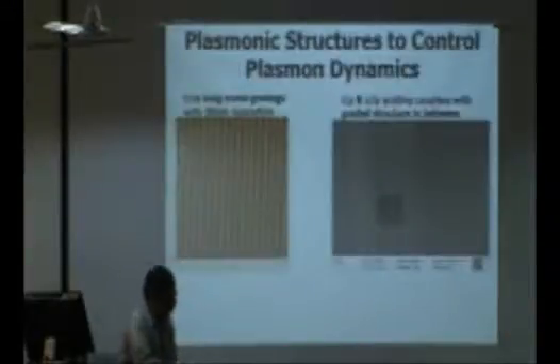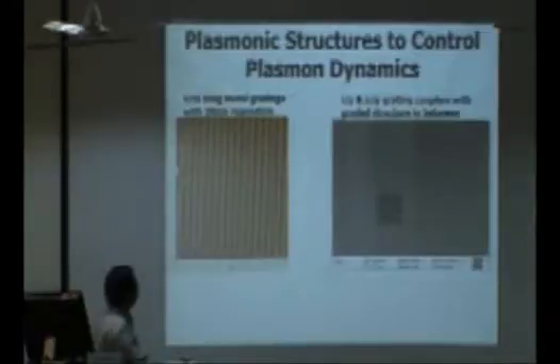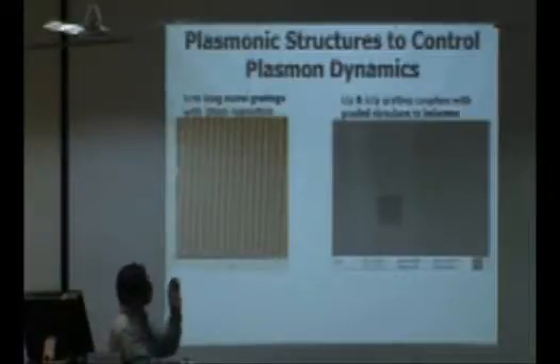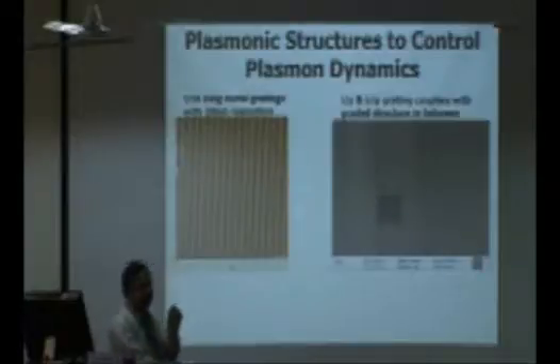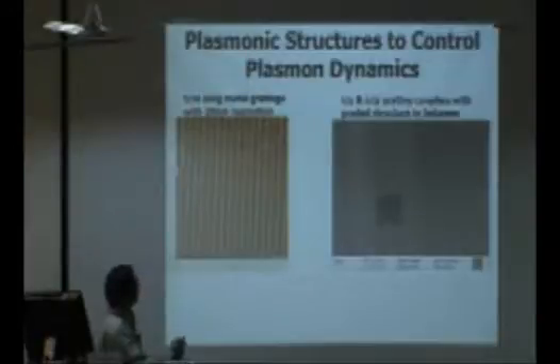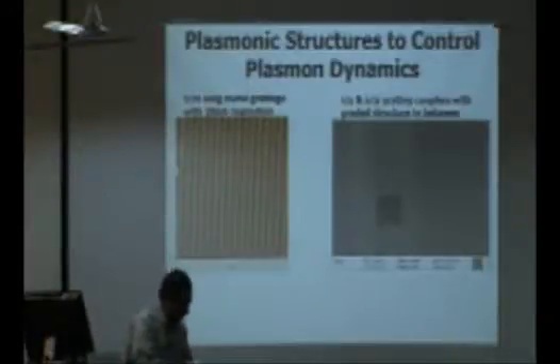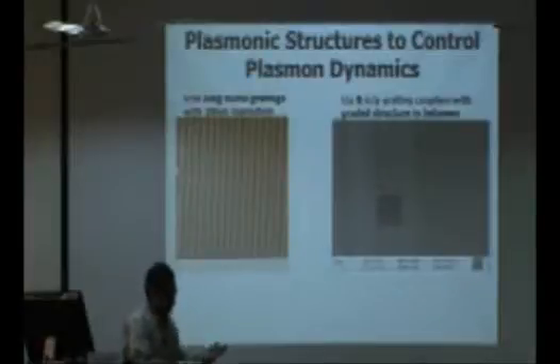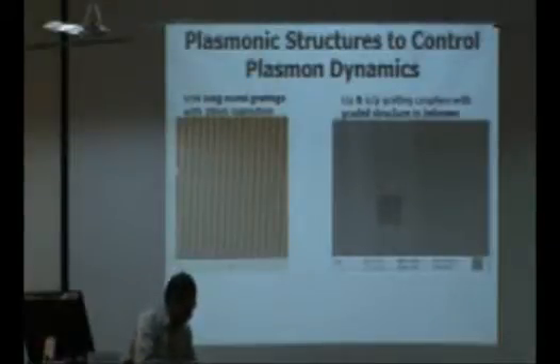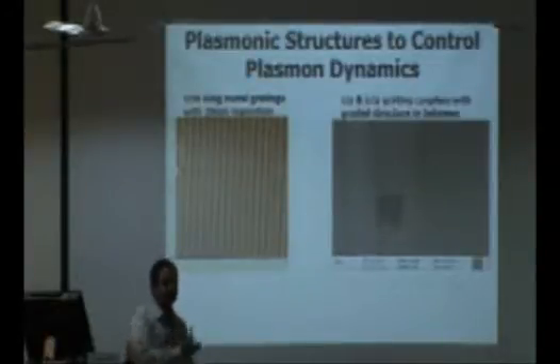So we also look at novel plasmonic structures. For example, these are incoupling and outcoupling gratings, and in between we have this graded grating structure, which is designed such that from one period to the other the period is kept constant, but the groove width is changed by a precise 10 nanometers. So the idea is to look at plasmon dynamics using these kinds of structures. For example, for studying Bloch oscillations, you need this periodic structure with a linear gradient.